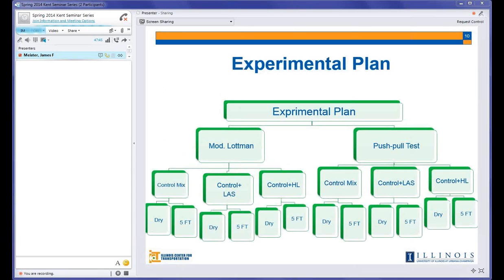This is the experimental plan. I will not go into details, but as mentioned, there are 2 tests. For each test, we now have 3 mixes: the control mix, which is moisture susceptible, the same mix with liquid anti-strip, and the same mix with lime. All have the same aggregate gradation, everything. The only difference is the addition of liquid anti-strip or lime. And for each mix, for each test, we tested 2 sets: the unconditioned and the conditioned.